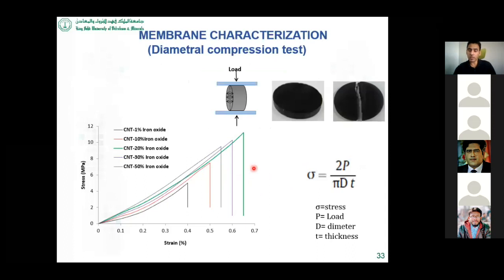Again, we found that these membranes have excellent mechanical stability, and we performed diametrical compression test for these membranes. All the membranes have pretty good strength. Again, we found that membrane with 20% iron oxide loading has good strength as compared to the other membranes. By the way, in water treatment, mainly this type of strength is not required. Even the smaller strength might be okay. But if you want to apply these membranes for other applications, or if they can be exposed in aqueous solution for a longer time, then maybe this type of test will be useful to predict the performance of this membrane.